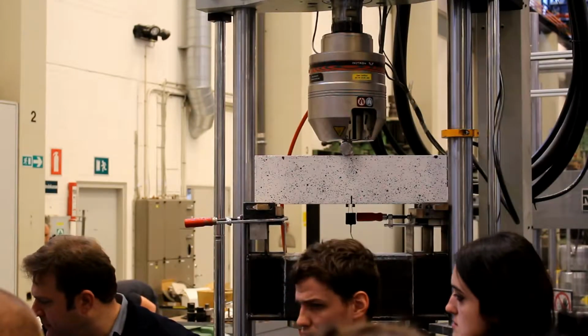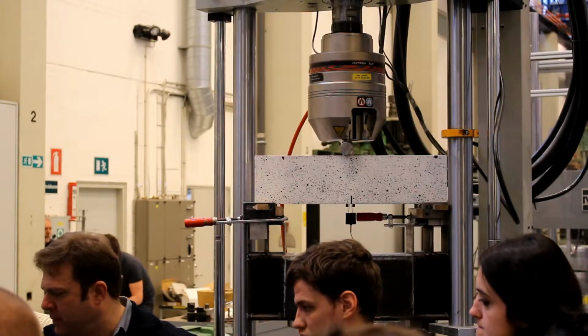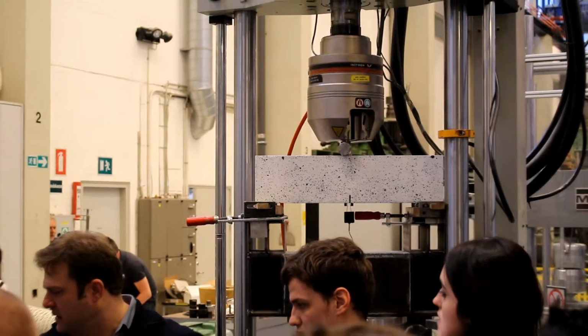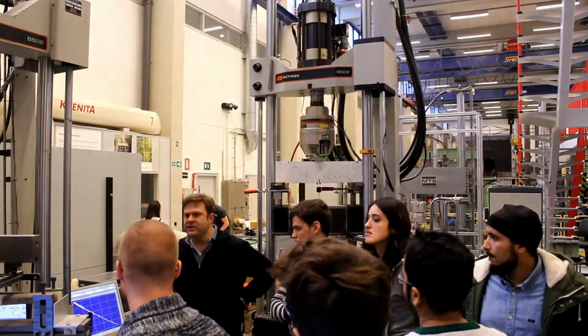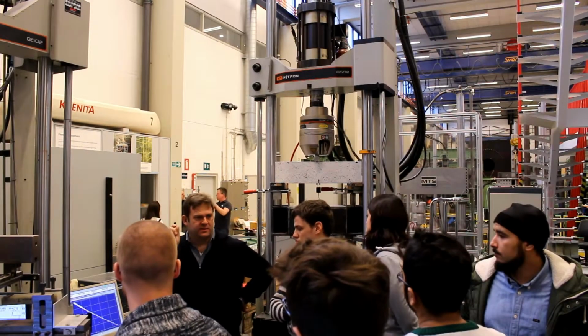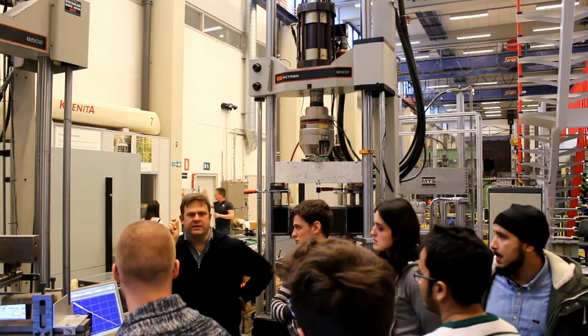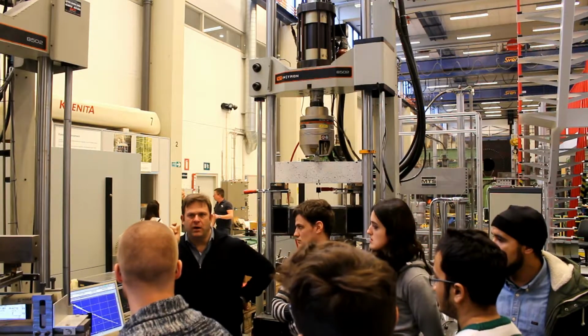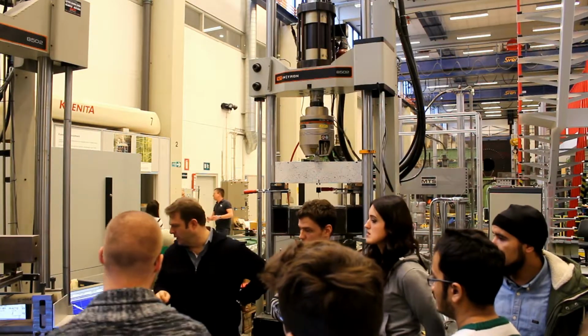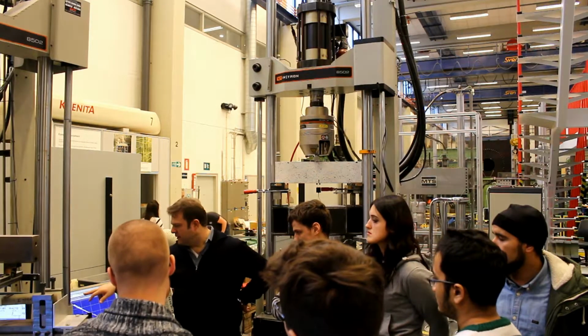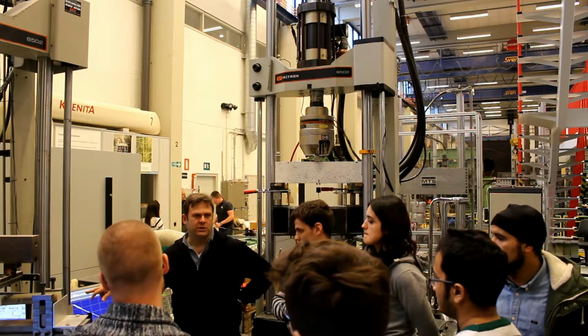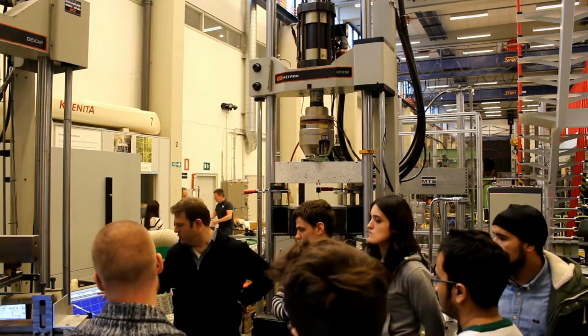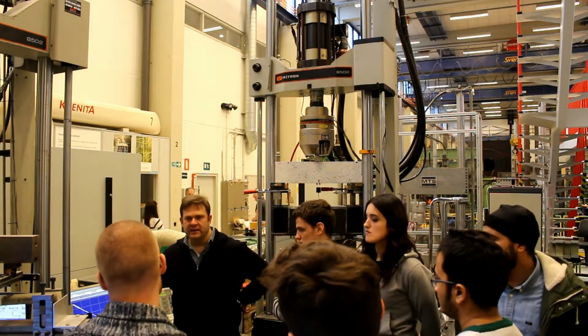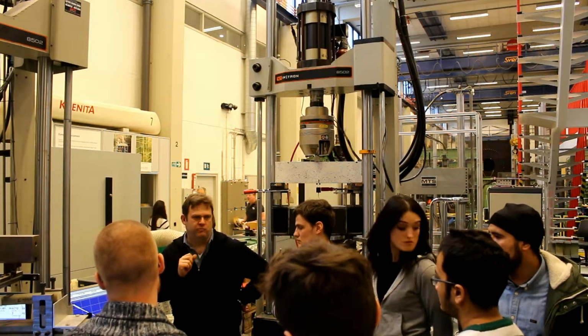So as the load goes up, we are now at 6 kilonewtons, and the crack opening has increased by 10 microns, 10 micrometers, a hundredth of a millimeter. Very small. But once we reach the cracking load of this specimen, you will see that the crack opening jumps up very quickly.